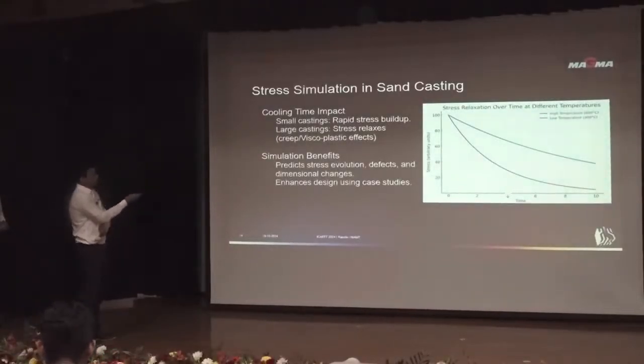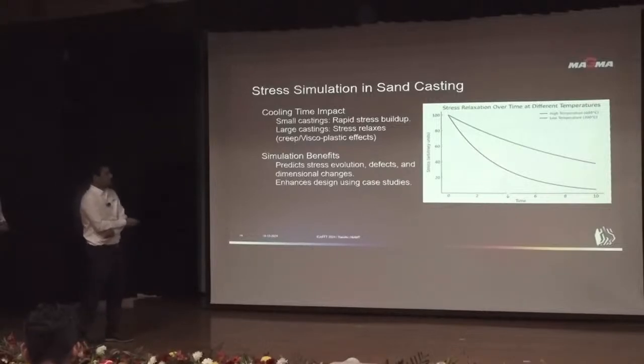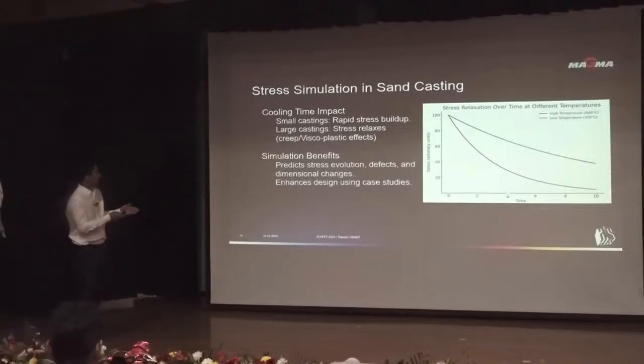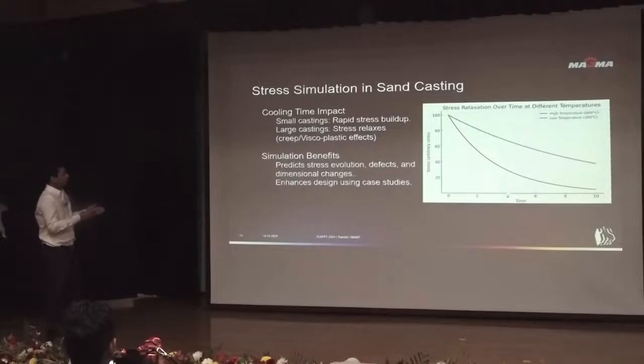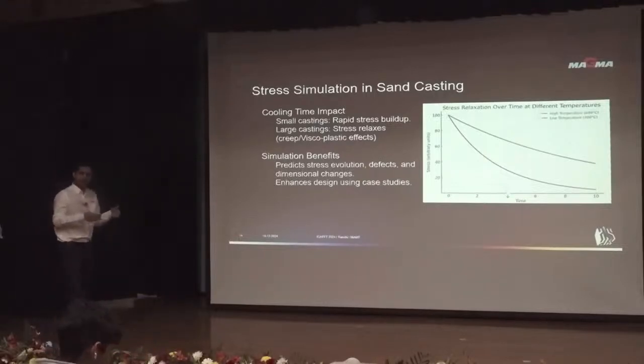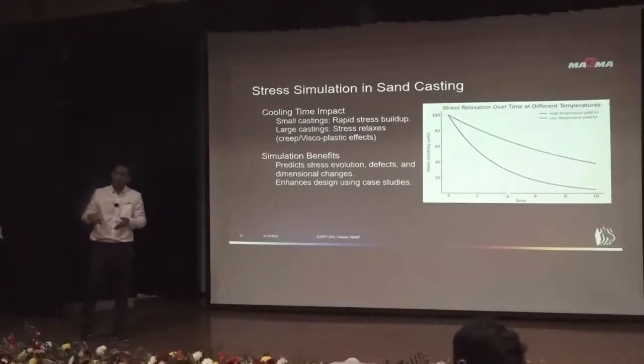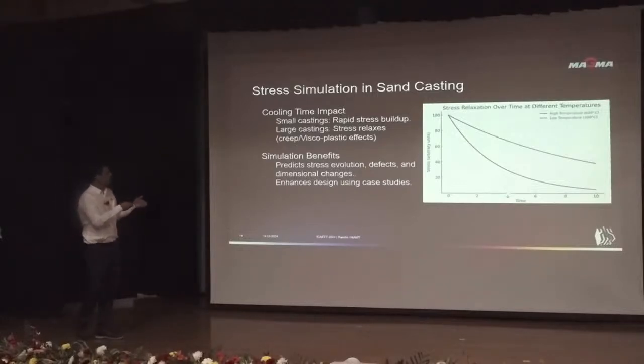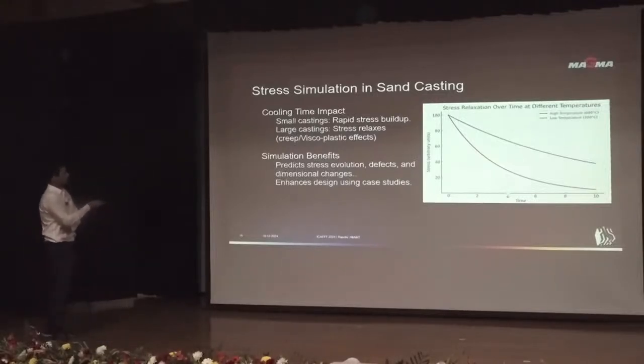As you can see in the image, stress relaxation over time for large castings has a different impact on the stresses. We call it the creep viscoplasticity effect. In large castings, because the casting has a lot of time to cool, the stress relaxation as per the creep effect will relax the stresses within the castings. So the simulation benefits are that they predict the stress evolution, defects, and what dimensional changes are going to take place. And so that's how we can enhance our design.